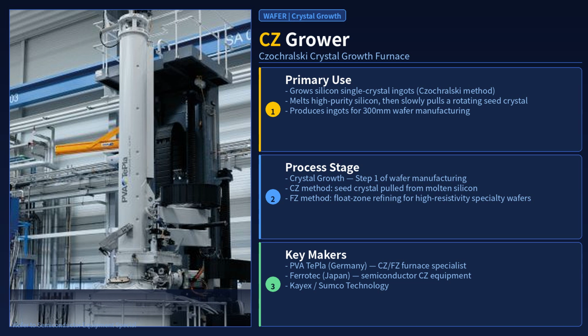To produce a 300 millimeter wafer, you need an ingot with a diameter of at least 300 millimeters. Keeping impurity levels and crystal defects extremely low throughout this process is absolutely critical. Key makers include PVA Tepla from Germany and Ferrotec from Japan. In addition to the CZ method, the FZ, float zone method, is used for high resistivity specialty wafers.